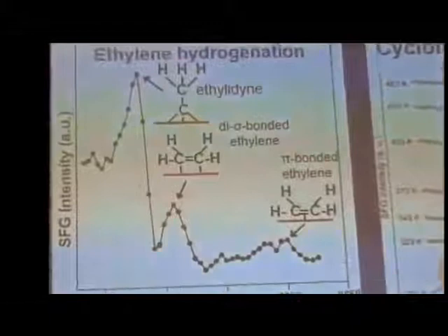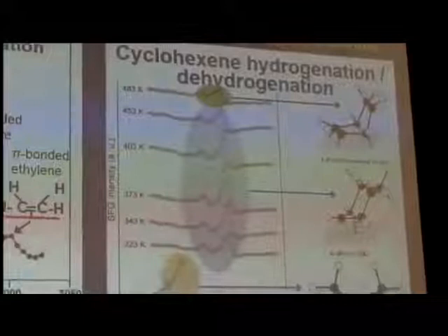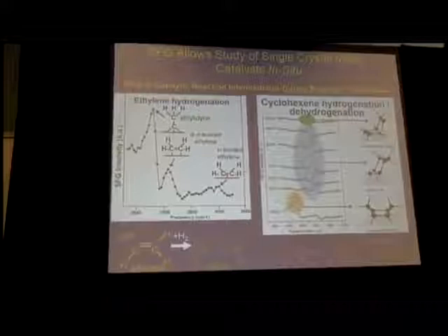As a result, you can see reaction intermediates. In ethylene hydrogenation, you can see three species on the surface — one that turns over, and two spectators — though isotope studies are needed to distinguish them. In cyclohexene hydrogenation you see 1,3- and 1,4-cyclohexadienes. The bottom line is we almost never see the product or the reactant, but something in between. This is not exclusive; more work is needed to make it more conclusive.